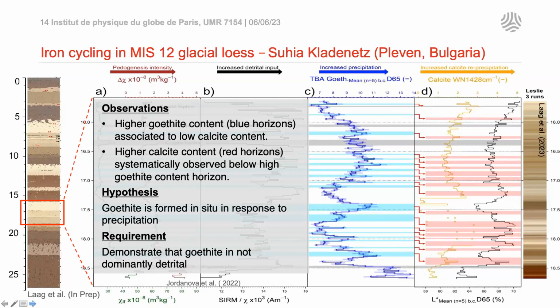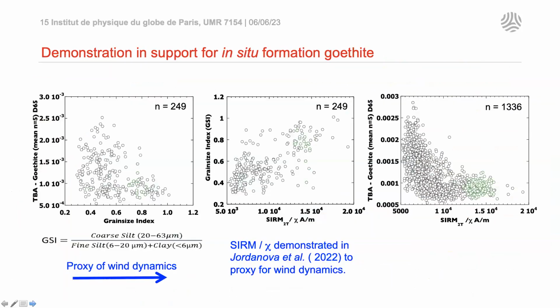So Christian's hypothesis, looking at this data set through this glacial period, was that goethite is maybe formed in situ, and that it's being formed in response to precipitation or water availability. So he wanted to attempt to demonstrate that this was true. So the first step would be to demonstrate that the goethite is actually not coming in with the parent material as coatings on the grains, but is actually being formed in situ, so that it is not dominantly detrital. That's what he had to try to demonstrate.